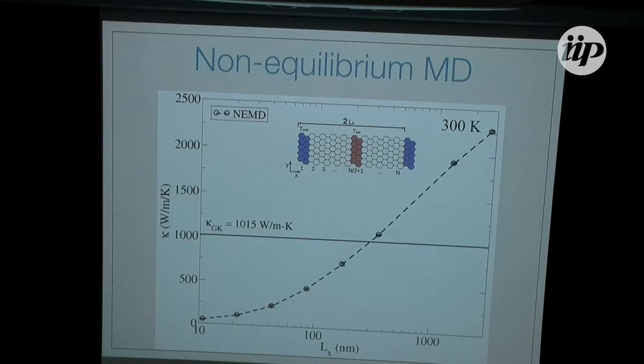Now we go on and do that for graphene, and what we see is that the thermal conductivity keeps increasing. This is for 300 K, with the non-equilibrium method. I actually have two thermostats there, and we do simulations up to almost 3 microns, and the thermal conductivity keeps increasing. This is a linear-log scale, so the thermal conductivity is going with the log of the system length, which is good in a way if the material really was two-dimensional.